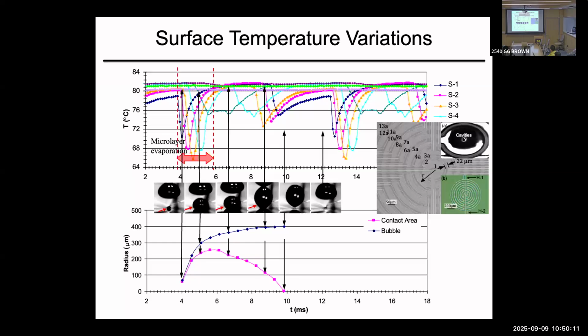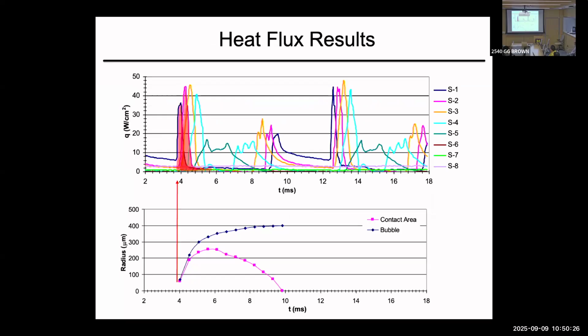So I associated this first event, between the bubble and the interface, with microlayer evaporation, and associated the second stage with transient conduction, based on all the data that we have. If you look at it in the context of heat flux versus time, you see these spikes at the interface of the solid and the bubble, indicative of microlayer evaporation, and then the transient conduction happening there.